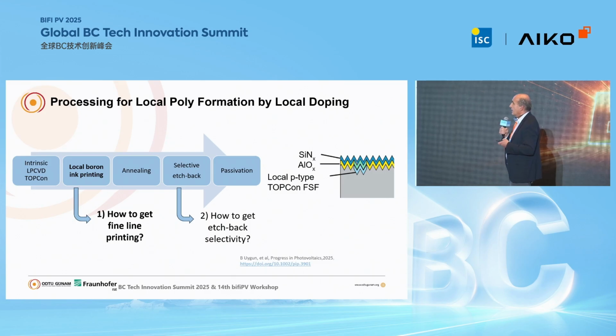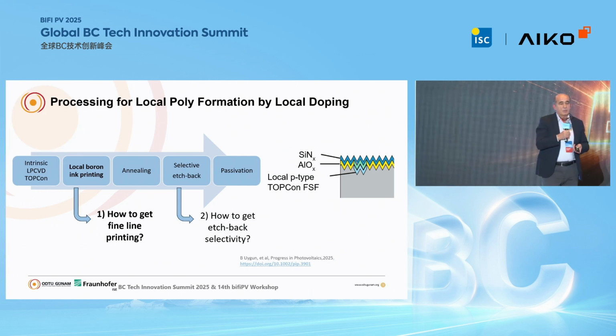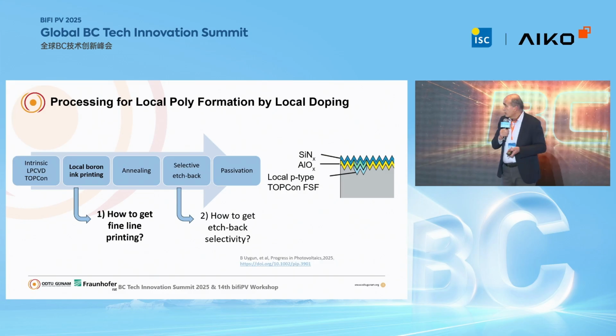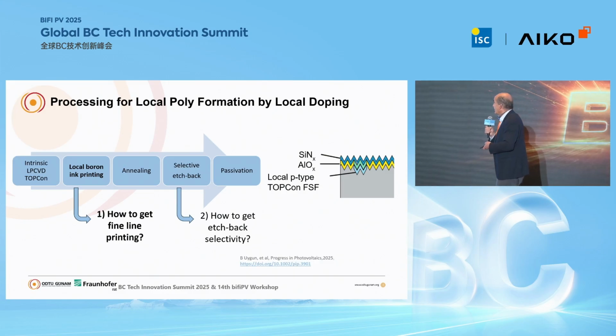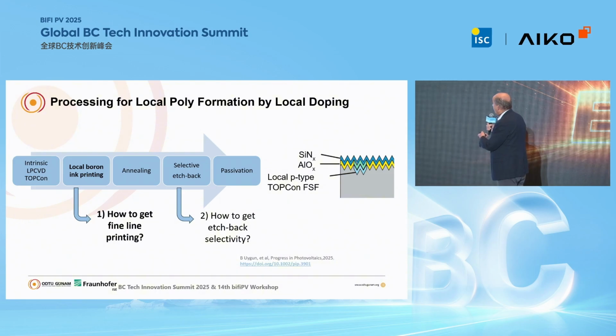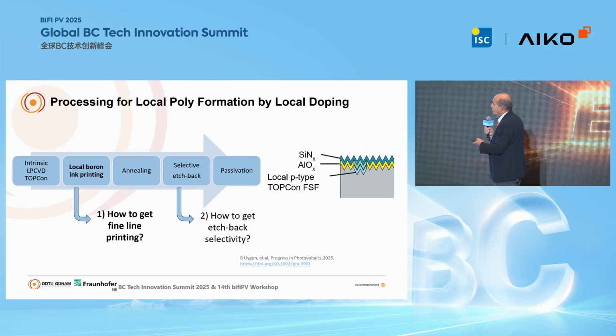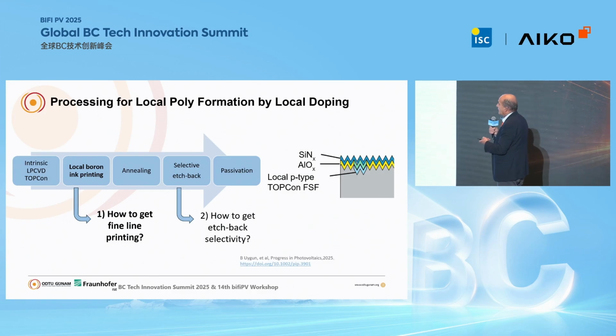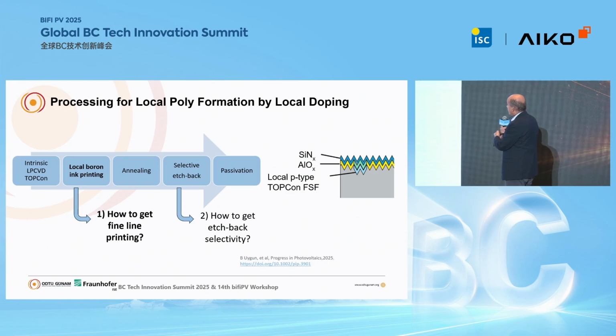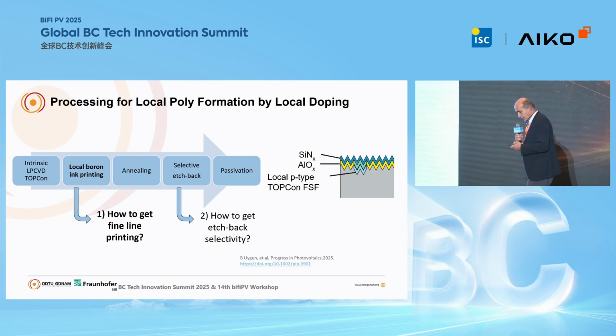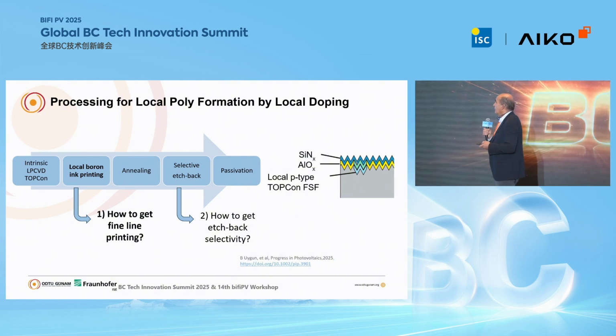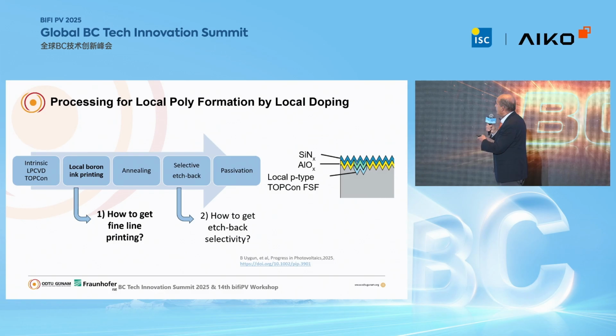selective etching by alkaline solutions. We know that heavily doped silicon is very slowly etched by alkaline solutions. So in order to use this property, we created heavily doped, boron doped region under the metal layer by using local boron ink printing. Following the annealing, the structure is etched back. So this region is not etched by the alkaline solution, so the remaining part is etched away. So you create the patterning on the surface. And then we put alumina and silicon nitride to test the passivation.